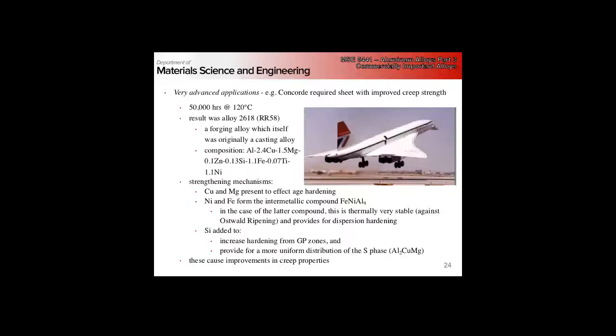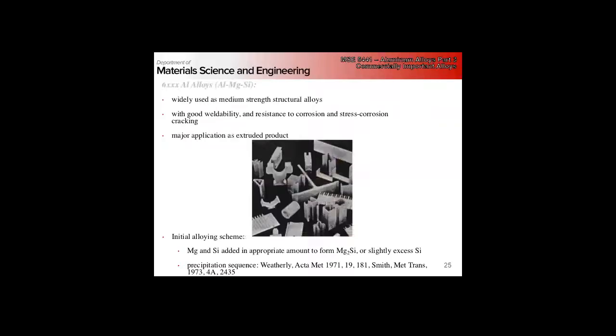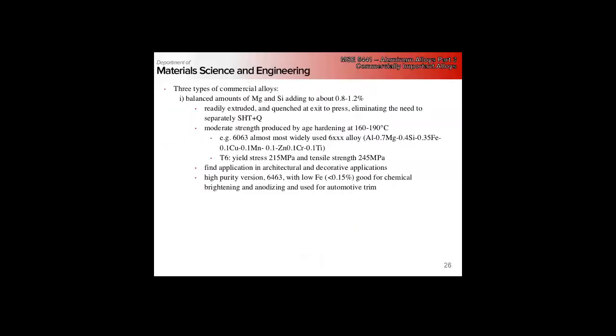Remember our age hardening curves for a lot of these alloys. What would happen to most aluminum copper alloys if we were to age for 50,000 hours at 120 C? How long would we remain in our high strength condition? If you think about the binary, after about 100 hours at these sorts of temperatures, we're completely overaged. We're way down the backside of that curve.